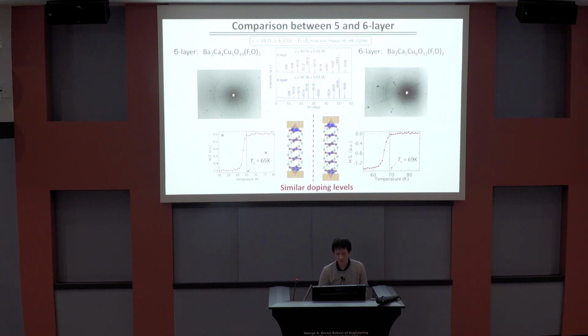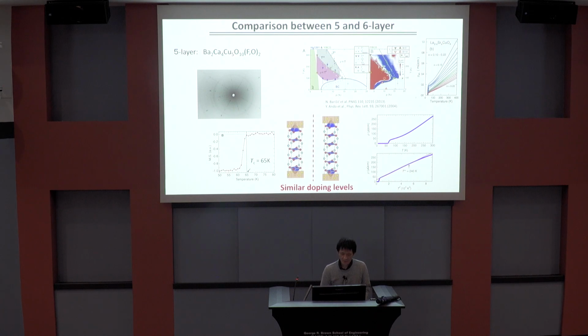The Tc is almost the same, which means carrier concentration is almost the same between the 5-layer and the 6-layer. And the resistivity shows a T-square dependence, consistent with other underdoped cuprates. So our sample is located in the very heavily underdoped region.